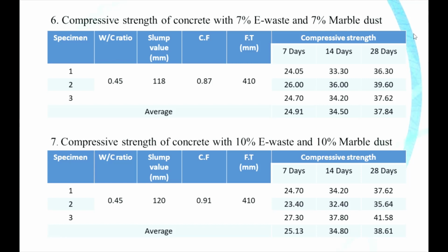The averages of strength at 7 days is 24.91 megapascal. At 14 days there is a strength of 34.50 megapascal. At 28 days there is a strength of 37.84 megapascal. So for the compressive strength of concrete with 10% of e-waste and 10% of marble dust addition, the averages of strength are 25.13 megapascal, 34.80 megapascal. At 28 days there is a strength of 38.61 megapascal. So as we see, there is a slight increase of strength with the addition of marble dust in the e-waste.